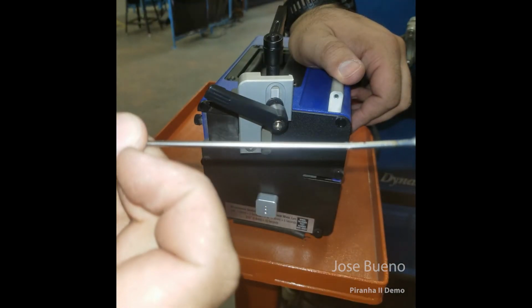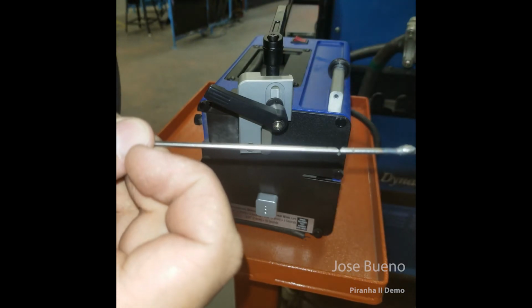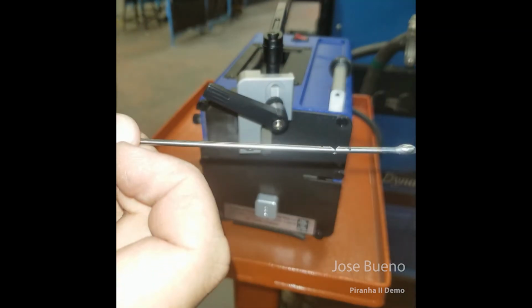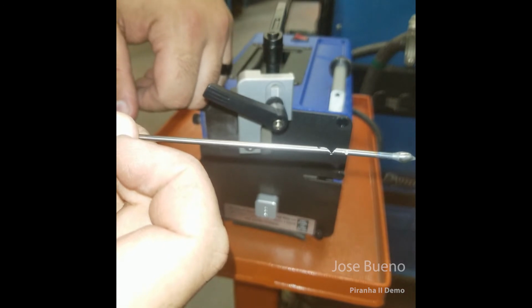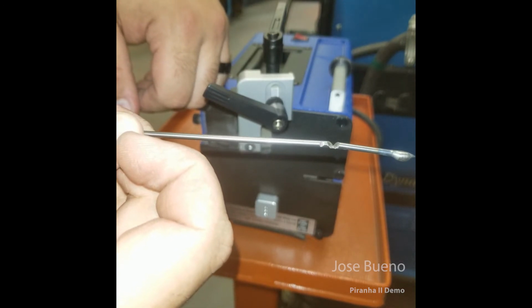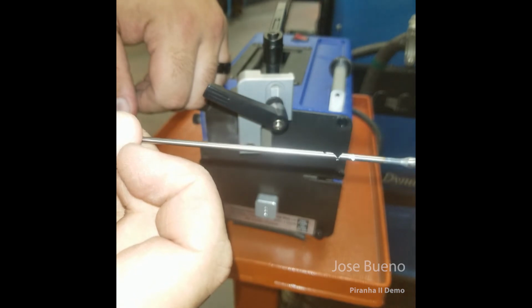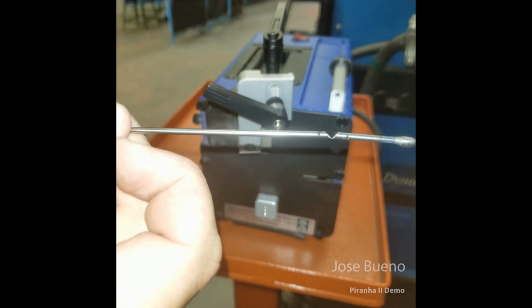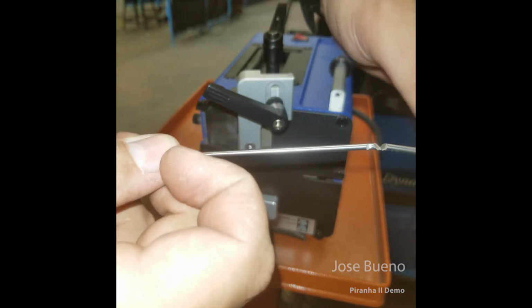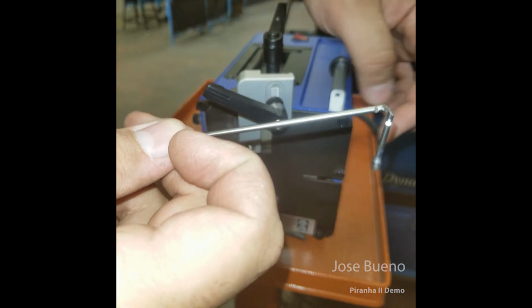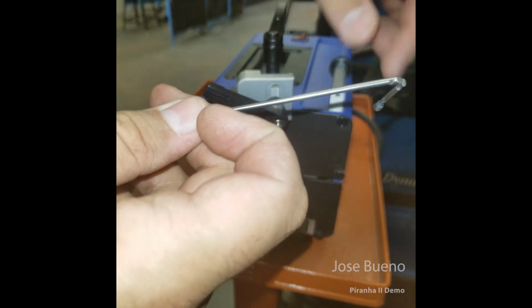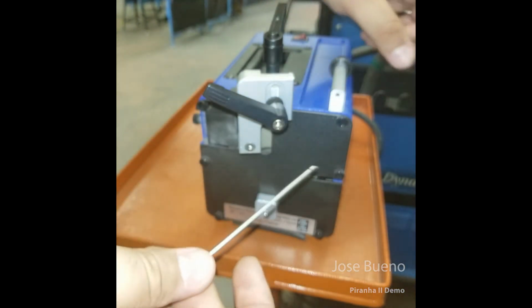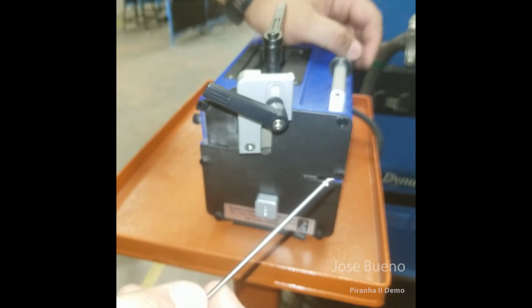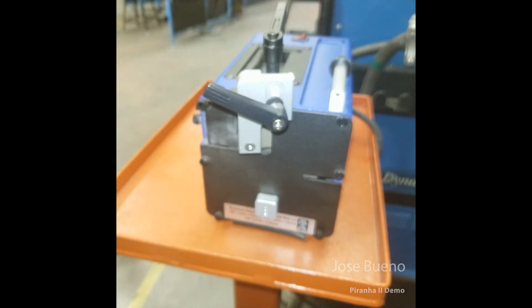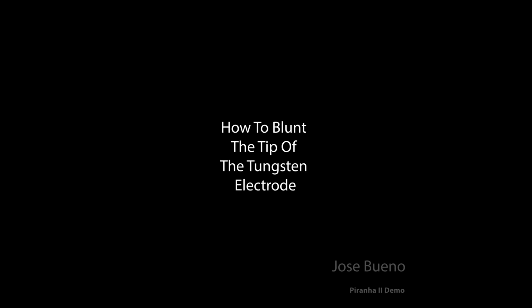And here you can see multiple notches in the tungsten, but you can see one in the middle that goes almost all the way through. I wasn't being as careful as I should have been, so whenever you're using the notching feature on the Piranha 2, make sure to pay a little bit more attention than I did. Also, notching out this much material out of the tungsten, it's going to heat up. Remember, that abrasive disc is removing material, and so friction is going to create heat. And actually, the tip of the electrode, as I'm taking it off, is quite hot. So please make sure that in order to do this, you either have pliers or you're wearing gloves.